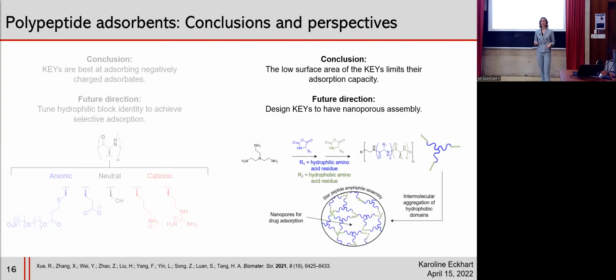A second future direction for this project is increasing the surface area of the keys. So we found that through the KL values, the low surface area of the keys is really what's limiting their adsorption. So if we could design a system that's more three-dimensional, such as a star polypeptide, we might be able to access some intermolecular aggregation of the hydrophobic domains that create these nanoporous pockets that could be used for drug adsorption.